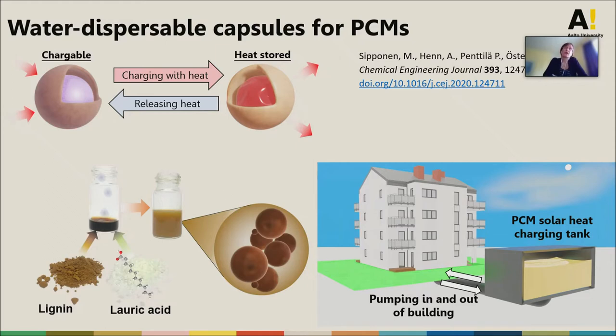So while the coating was an example of something that you can maybe think about that lignin could be useful for, this is a typical example that you cannot use the crude lignin for. So this works only because we can make these particles. What we have done is that we co-precipitate the lignin with a phase-changing material. So we form these hybrid particles. And the phase-changing material can be a fatty acid, in this case, a lauric acid, for example. And it's incorporated: the lignin forms the shell, and then we have the phase-changing material inside.